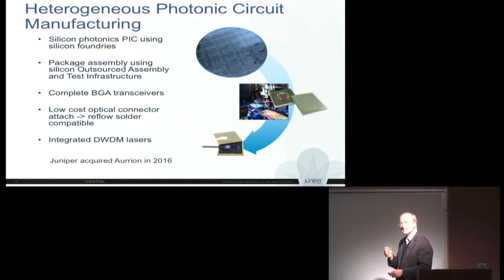Most of this, by the way, is not hermetically sealed, and that's a big change. I didn't point that out earlier, but the big problem in indium phosphide or gallium arsenide lasers is facet degradation. That's where most defects start and propagate in and kill the lifetime, and often require hermetic packaging. In this case, all that's exposed to the air is a silicon waveguide. The III-V is completely buried in an SiO2 layer that's fairly thick. So there's no need typically to hermetically seal these devices.